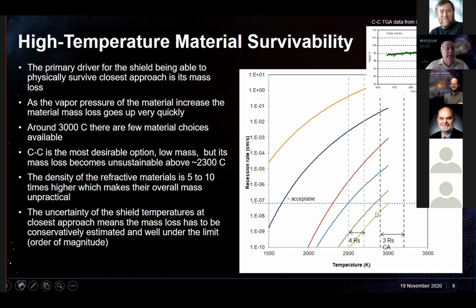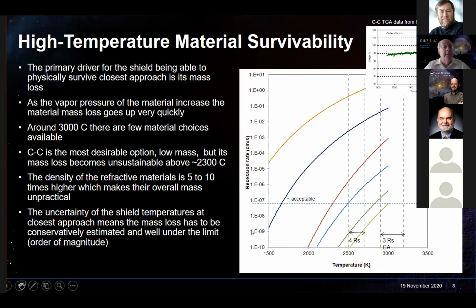So tungsten is, if you're just looking at materials that work, your material of choice in the sense that it has a very low vapor pressure, and I guess that's its main claim to fame. It is also extremely heavy and it's not a design material. It's a brittle material, it's a refractory metal. As we get up around 3000 degrees, if you say I have a certain temperature profile that I'm going through for a certain time, and you back-calculate that to figure out what allowable mass loss rate you can have, in the centimeters per second range, it's in this 10 to the minus 7, 10 to the minus 6 range.